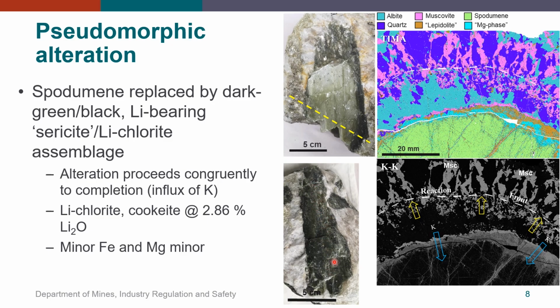Now, the white dashed line in both the mineral map and the potassium distribution map we interpret to mark a muscovite decomposition front. During pegmatite alteration, muscovite is decomposed, releasing potassium, which in turn is incorporated during alteration of spodumene to form secondary potassium-bearing clays. Alteration progresses inwards along crystal fracture surfaces and cleavage planes until completion.